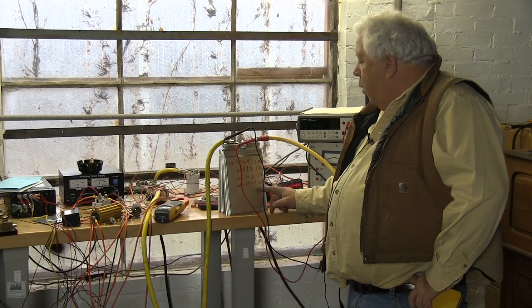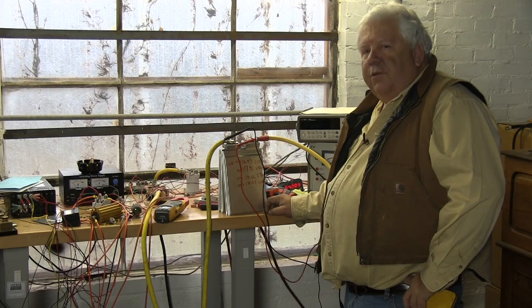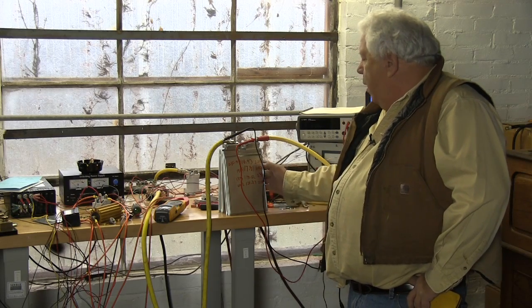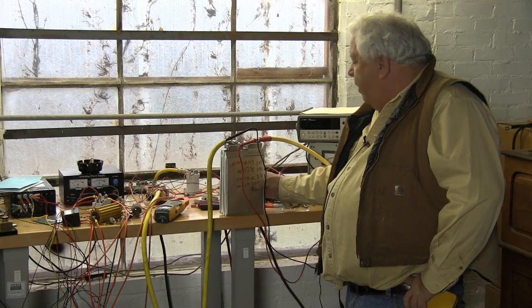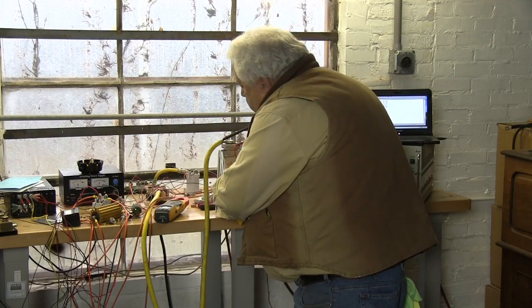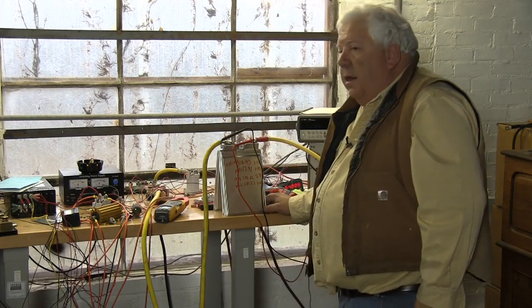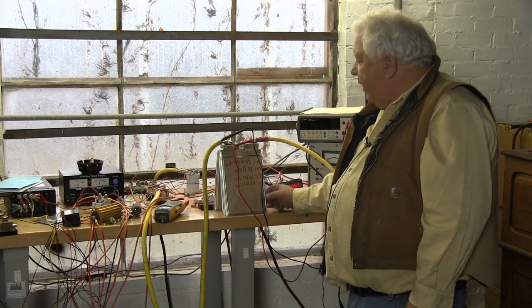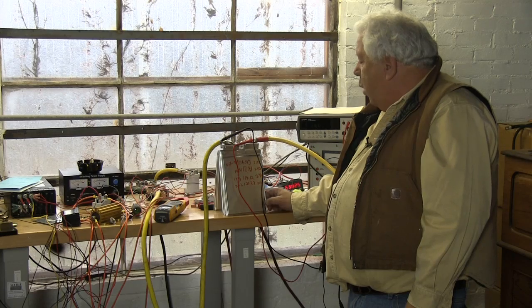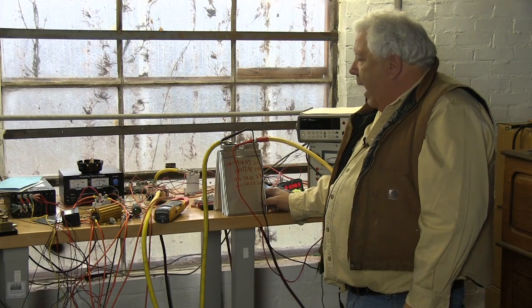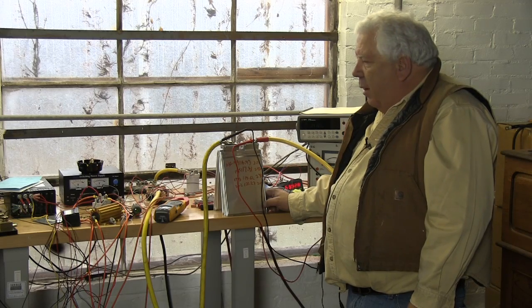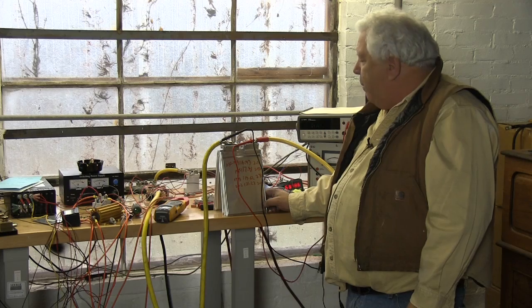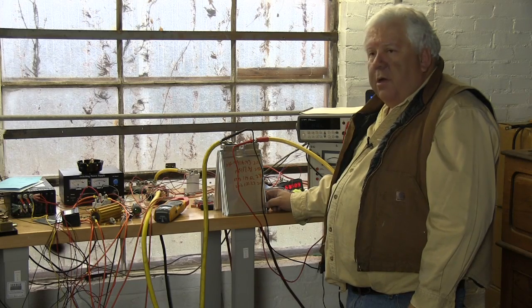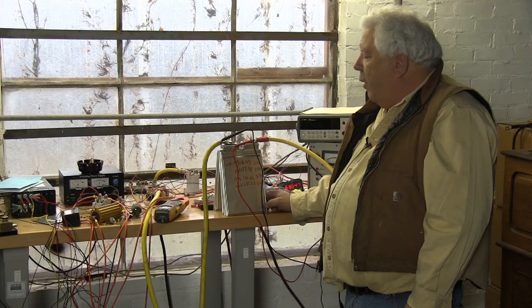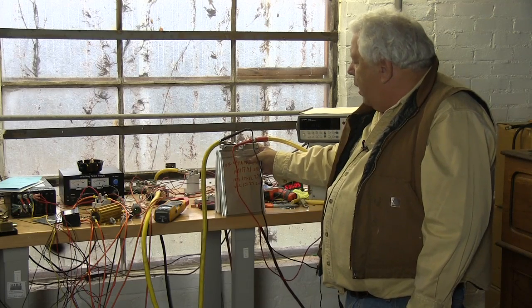and so we're going to see if we get 120 amps back in by 3.65 volts. Even though on this discharge we went down pretty close to 0 volts, about 0.1 volt on the cells, we're going to see if that has any effect, or if that's any part of our problem with the other ones. We did not drive them into reversal because we have 6 in parallel. We can't, but we took them quite low and quite below the 2 volts, and now we're adding current back in at 0.5 C, 60 amperes into our 120 amp hour cell pack. And if that comes out to 120 amp hours again, or even close thereof, I think we've got a good